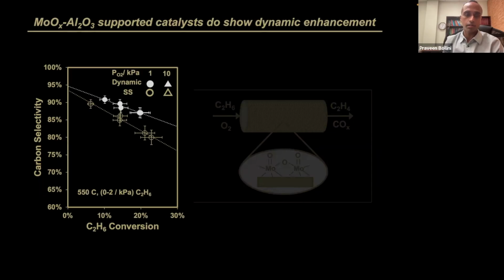So the data you see here, I'm plotting ethylene selectivity on the y-axis as a function of ethane conversion at a single operating temperature, in this case 550 degrees Celsius. And you see the steady state data in gold and the dynamic chemical looping data in white. And for a given value of ethane conversion, as you can see, you have a higher ethylene selectivity when you operate under chemical looping or dynamic conditions compared to when you operate under steady state.